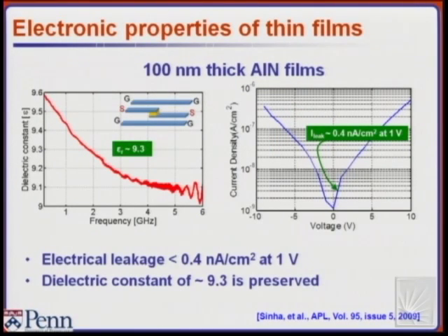And for 100 nanometer thick films, we also looked at the electrical characteristics over a large frequency range, because ultimately this device will be used to switch mechanical elements with signals in the hundreds of megahertz, hopefully gigahertz range. And the dielectric constant of these films actually stays pretty much constant across the entire frequency range. And the leakage is also very interesting, very small, 0.4 nanoamps per centimeter squared at 1 volt. This actually makes it better than 100 nanometer thick silicon dioxide, the oxide of your gate transistor, right? So the leakage characteristics are comparable.